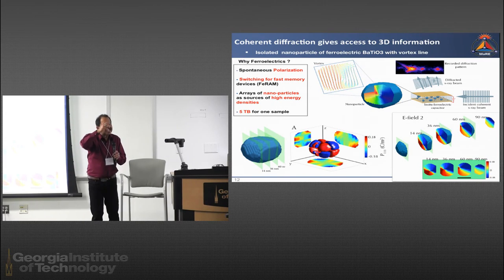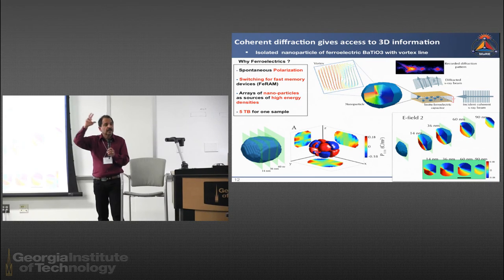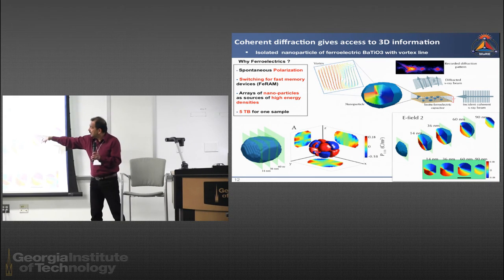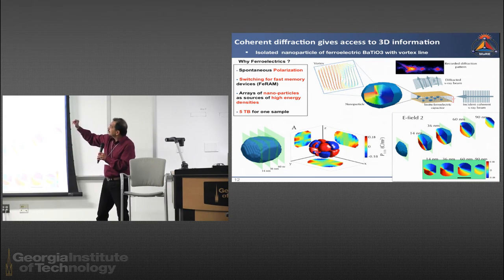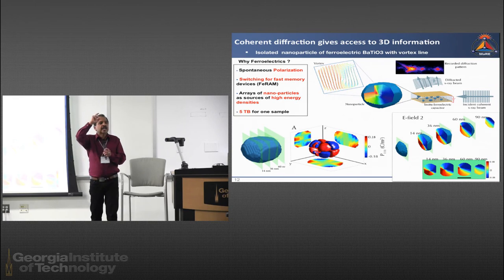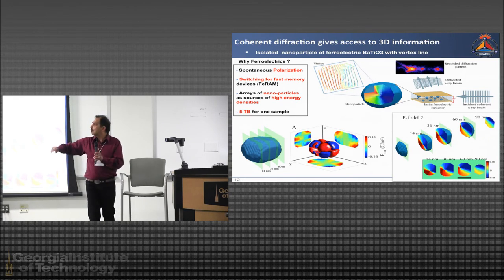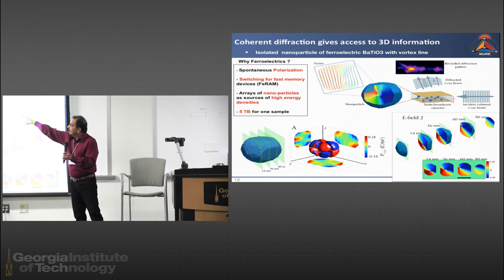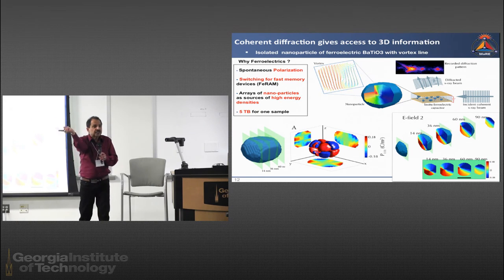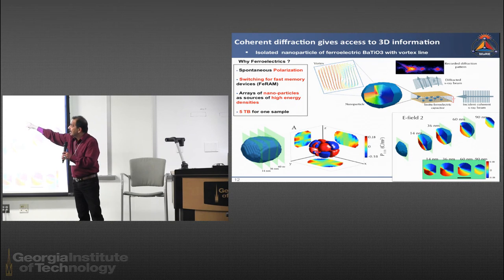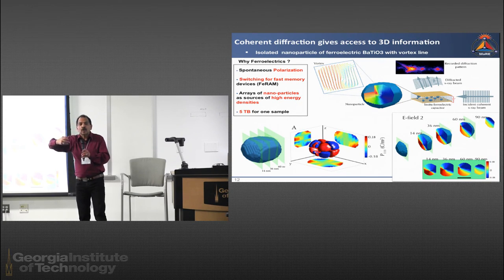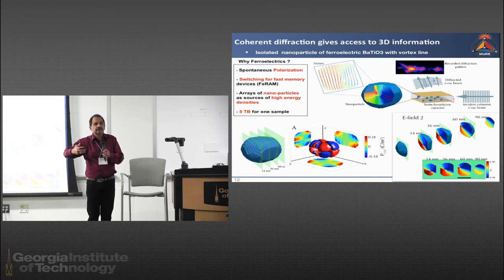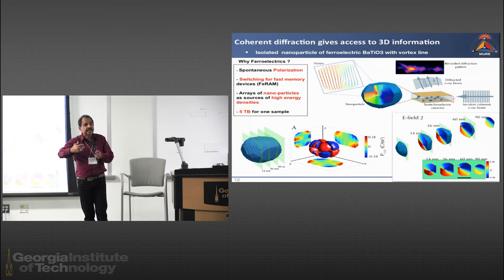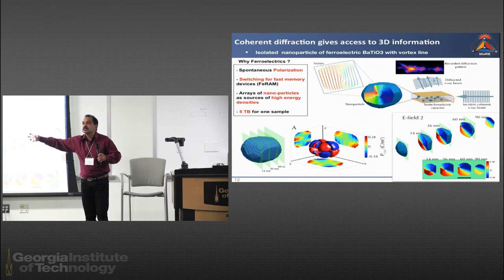It's really seeing inside. So it's a nanoparticle. It's about 19 nanometers. And it's a ferroelectric. Okay, ferroelectrics are very important because you're dealing with polarization switching. They're very important for FeRAM, ferroelectric RAM. And what you want to do is you want high density. Okay, so the way you get high density is by taking nanoparticles and essentially building arrays.